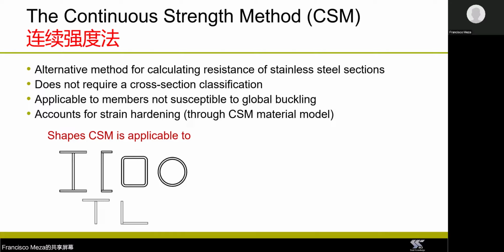Now, one thing that is very important to take into account is that in order to use the continuous strength method, the section cannot be susceptible to global buckling. So you will need to make sure that you provide a sufficient amount of restraint to your columns or beams to prevent flexural buckling or lateral torsional buckling from happening. And also, the continuous strength method is only applicable to the sections that you can see in this slide.